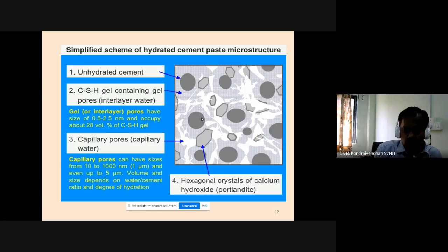Otherwise, you can say it's Portlandite. Actually, this is what gives the alkalinity to the concrete. That's why concrete initially has alkalinity. Even if you look at concrete alkalinity, the pH varies around 12 to 13.5. A good concrete has a pH of 12 to 13 due to the presence of Portlandite, which is liberated from the primary hydration reaction.